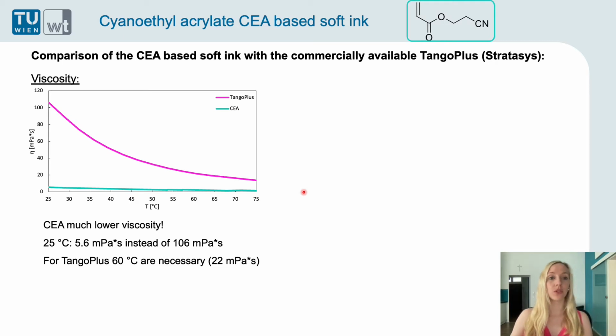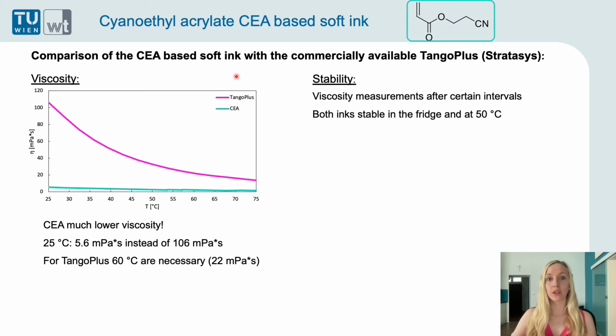At 25 degrees C, the viscosity is only 5.6 millipascal seconds, while Tango Plus shows a viscosity of 106 millipascal seconds. So for the Tango Plus, you would really need the 60 degrees C because here the viscosity is only 22 millipascal seconds. The next characterization was the storage stability. Here viscosity measurements after certain time intervals were conducted, and both inks are stable in the fridge and at 50 degrees C, so this is fine.